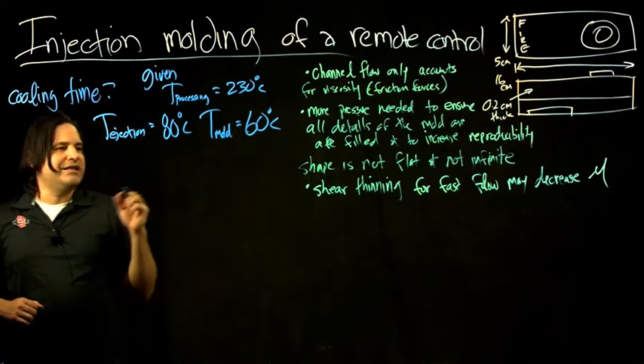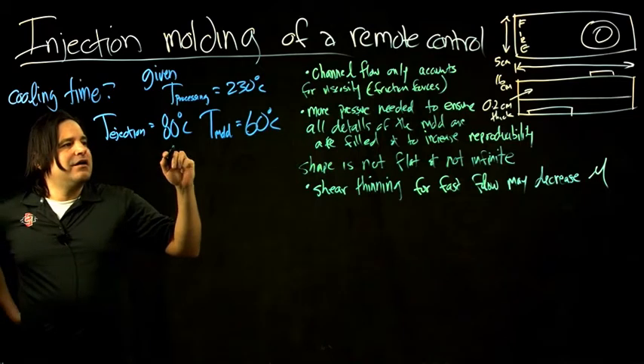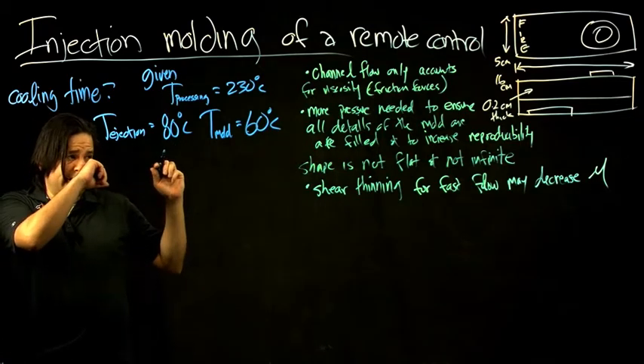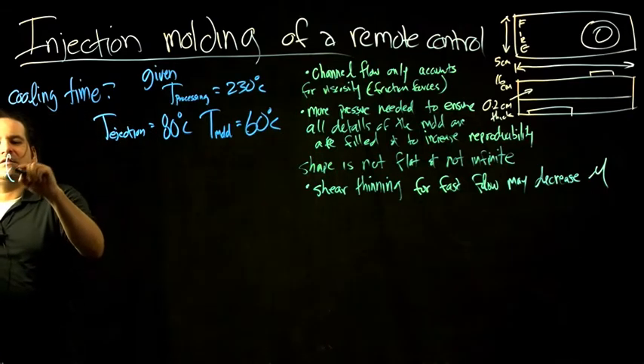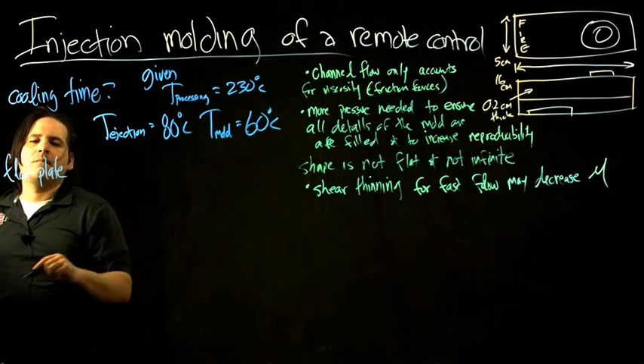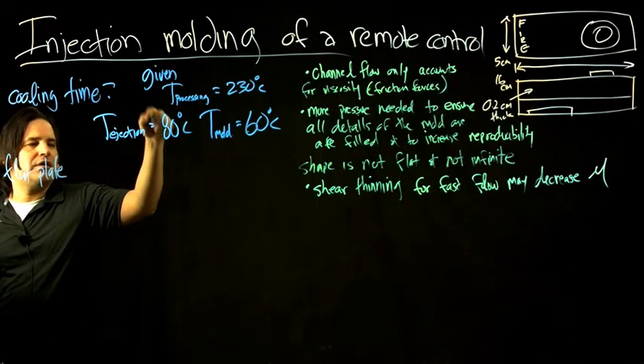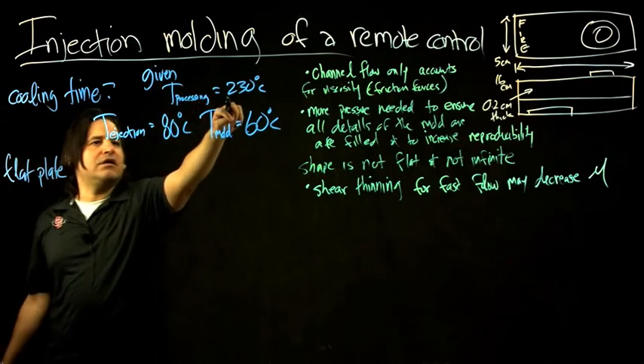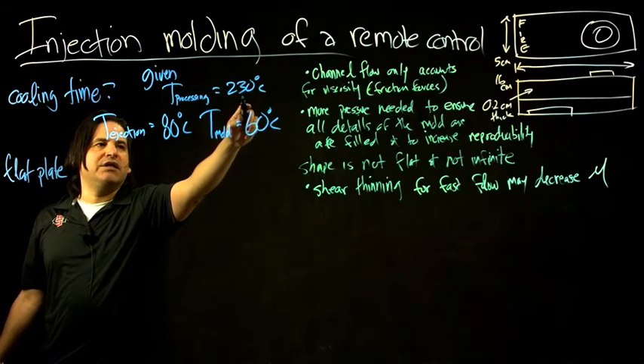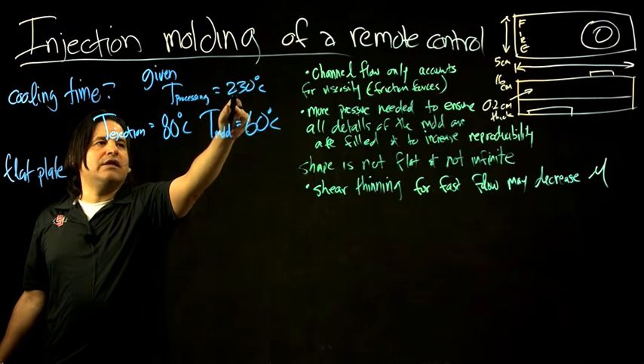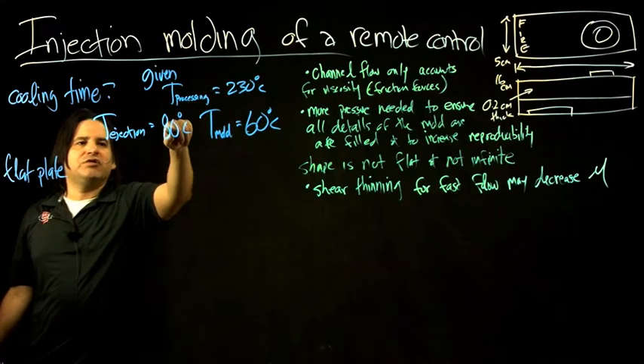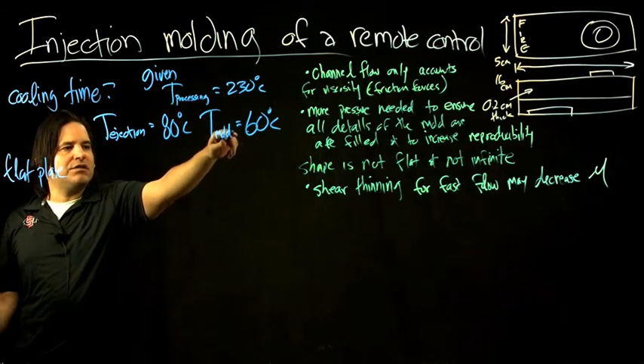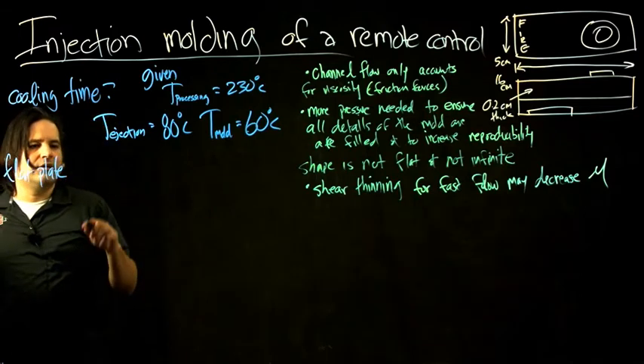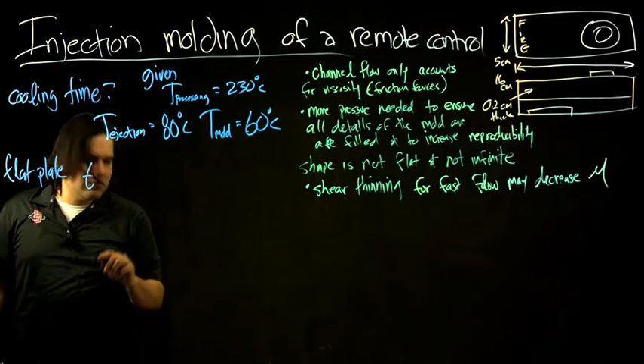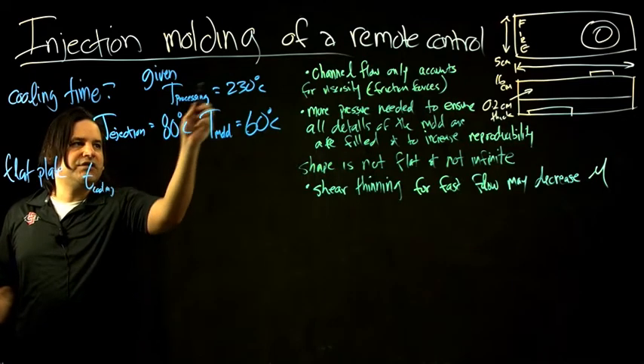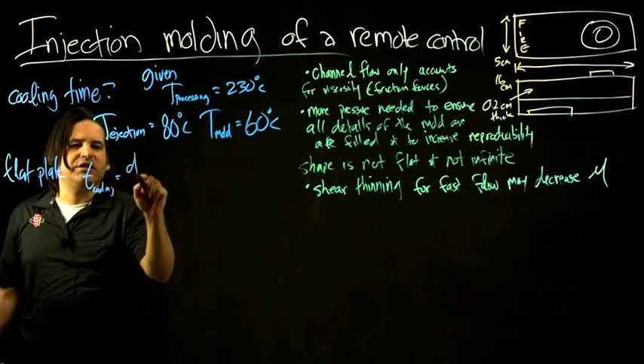Okay, so we won't do the heat transfer problem, but you can solve the energy equation, the heat transfer equation, for a flat plate again. So simplify this for a flat plate under these boundary conditions, reaching this final temperature. It will be an initial value problem. The initial value is that this melt is at 230, and the final value is 80 degrees Celsius, given some boundary of 60 degrees Celsius. You can solve that energy transfer problem, and what you would get is the cooling time to go from 230 to 80, given by this expression here for a flat plate.